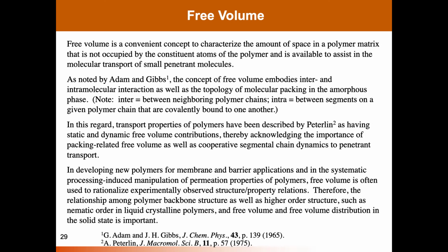We'll change topics a bit now, and talk about free volume and quantification of free volume. It turns out that one of the most important parameters describing rates of transport in a polymer is the amount of free volume or open space that's available to assist penetrants to undergo molecular transport. We often estimate this in polymers based on the density of the material, which I'll show in just a moment. And I would say that after 30 years in this business, if someone comes along with a new polymer and says, what would you guess its transport properties would be? The first piece of information I would want to know would be, what's the density?